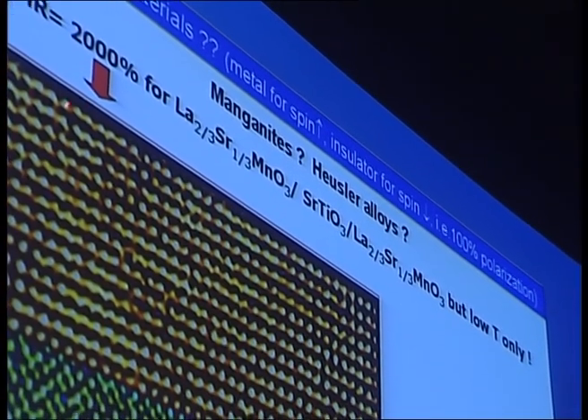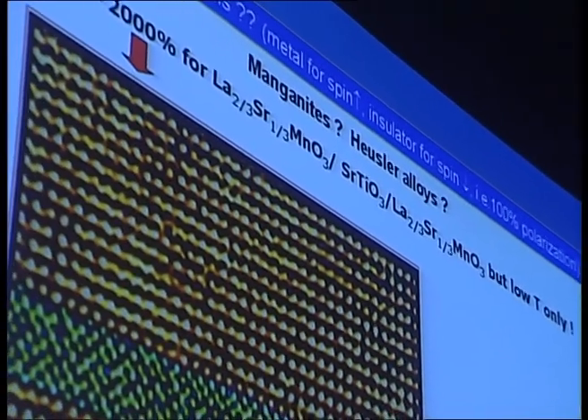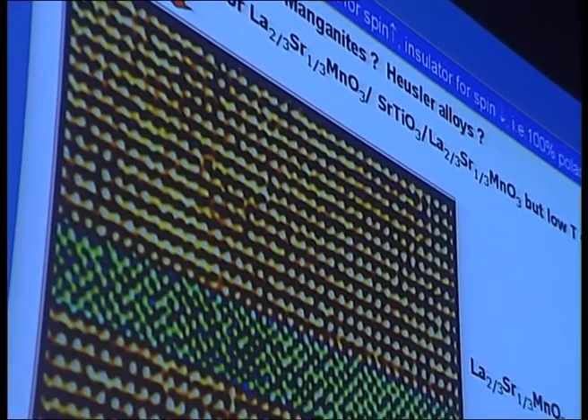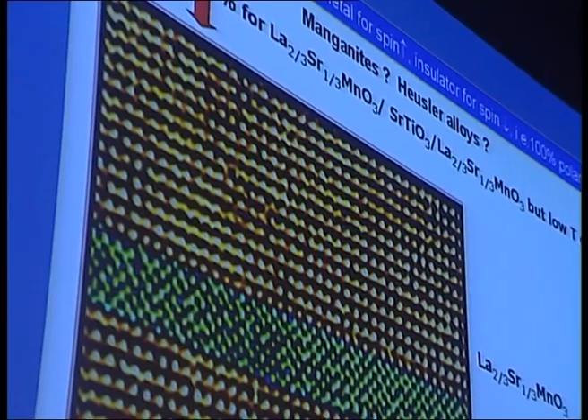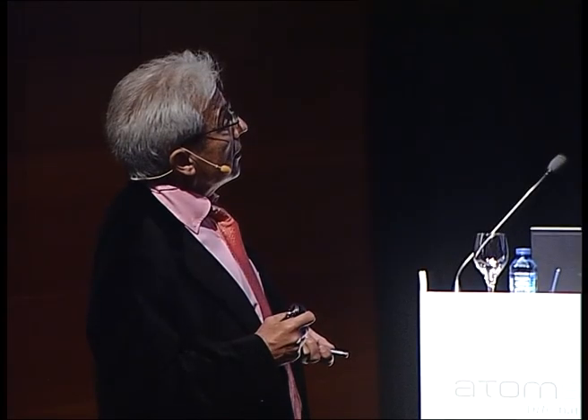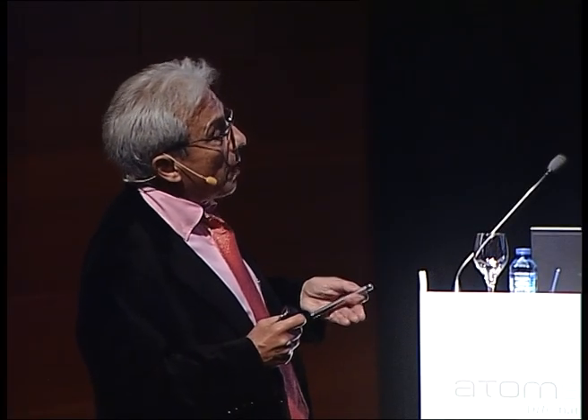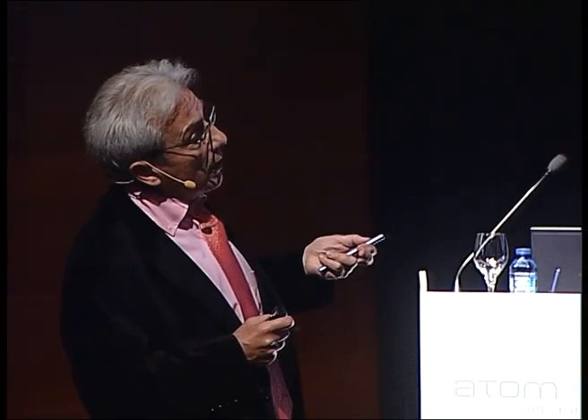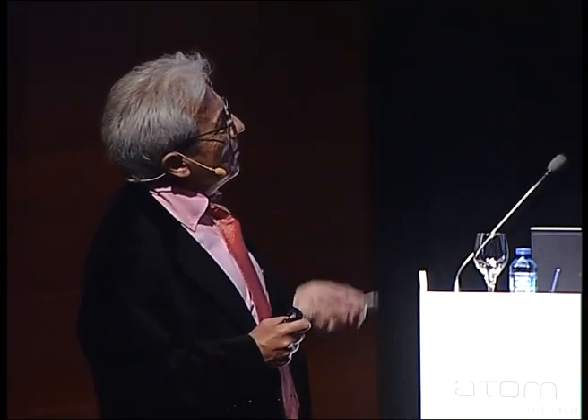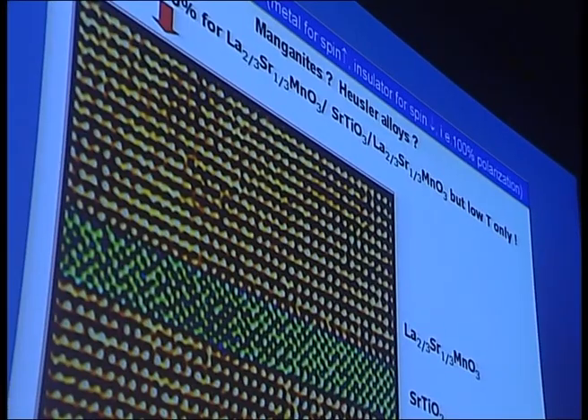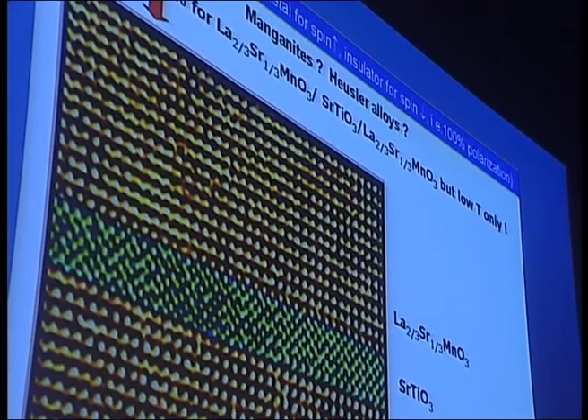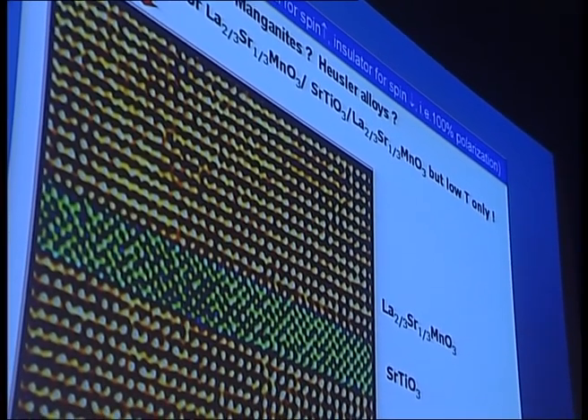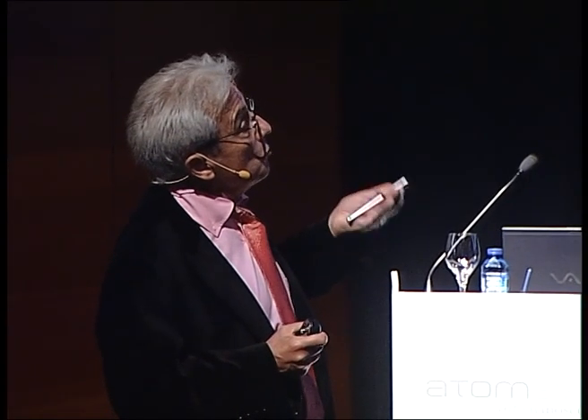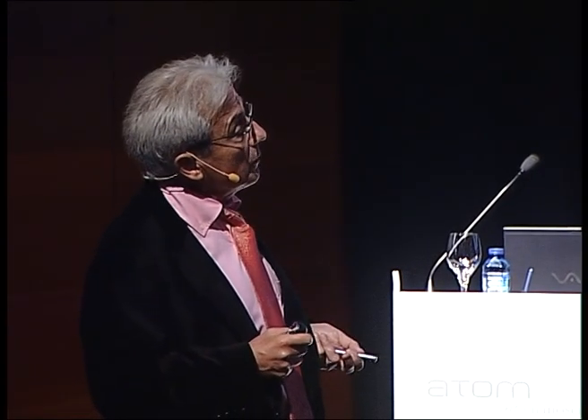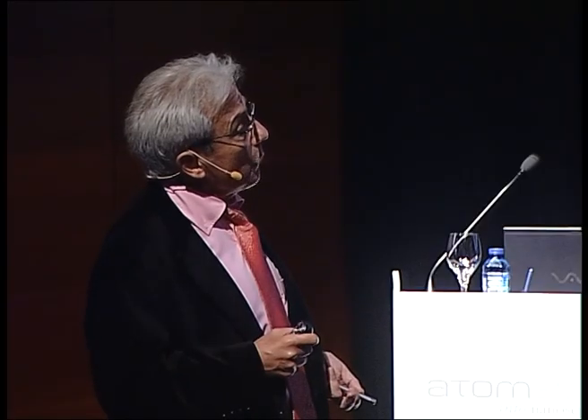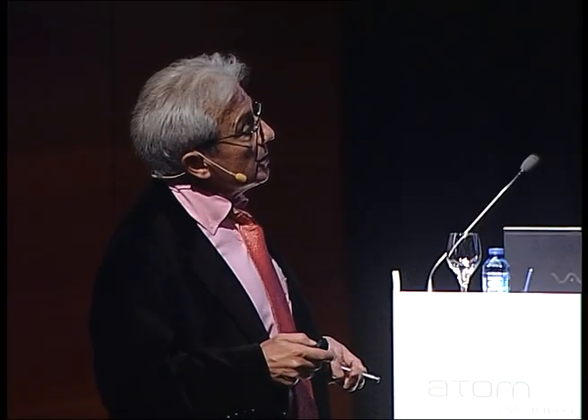For the moment, there are some very good results, for example, for this type of barrier that we have obtained, an increase by a factor of 20 between parallel and anti-parallel, but only at low temperature. So finally, the same difficulty in obtaining a good result at room temperature in this new magnetic material is one of the difficulties. And this direction of research has been relatively disappointing.